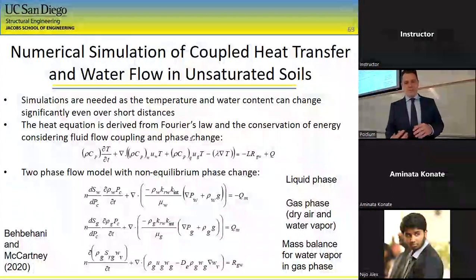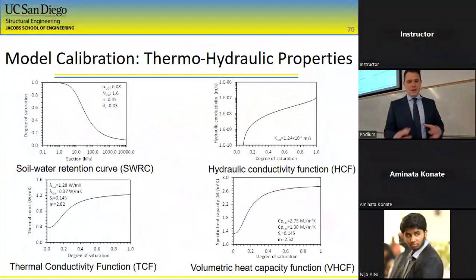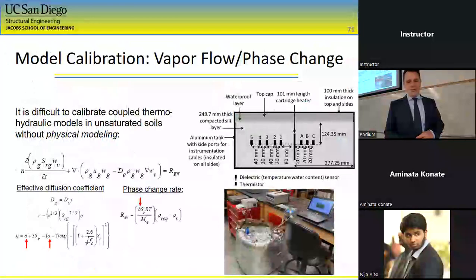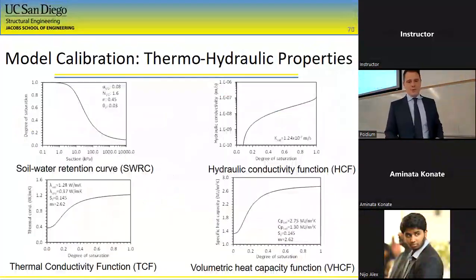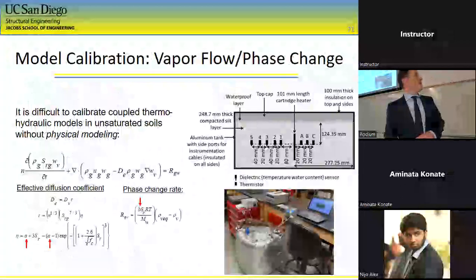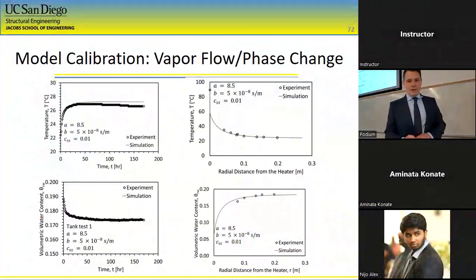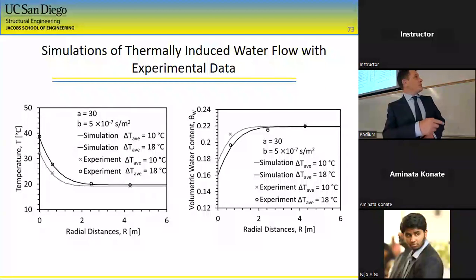So we had to come up with some coupled heat transfer and water flow models to look at this thermally induced drying in both liquid phases and gas phases. So we went for COMSOL with this. We had to have a lot of calibration. We did some tank scale tests just to get the parameters to put into this model. And we were able to, this is just the calibration, but then we were able to capture the trends in the experiments from our sensors and the tests. And with that, we could predict what the water content is right at the soil pile interface.